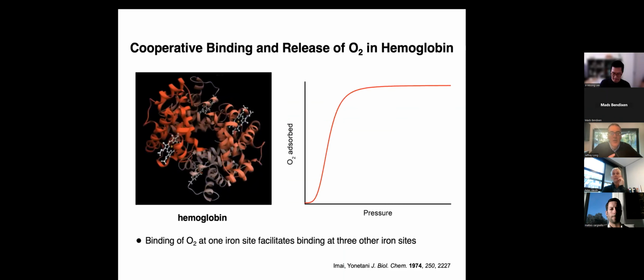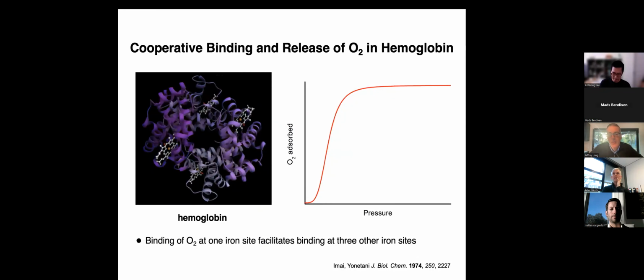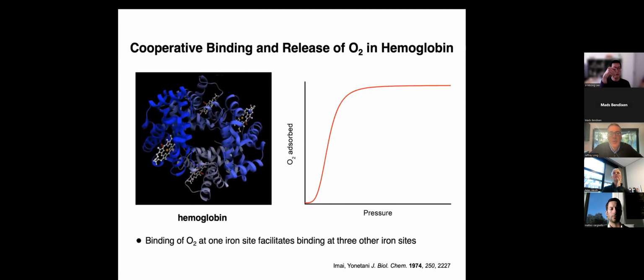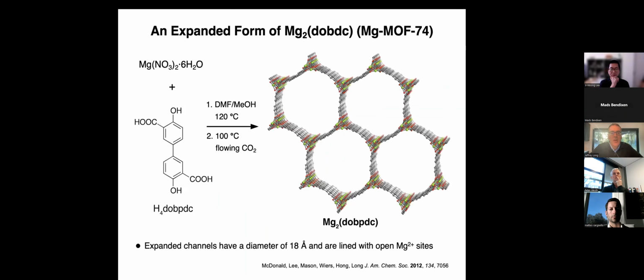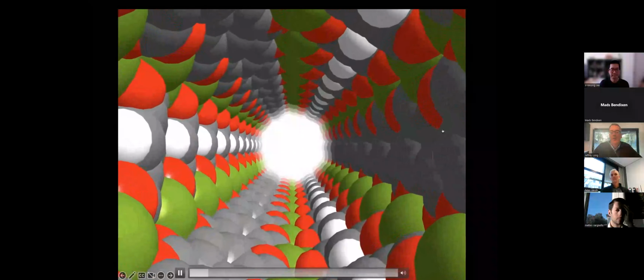And so nobody had seen this sort of thing in a dense form in a porous material until we serendipitously discovered it, not for oxygen, but for CO2. And the MOF that we found this in is one that is built on magnesium 2+ cations stitched together by this organic linker shown at the left. This linker is deprotonated 4 times, and that 4- anion stitches the magnesium ions together into a honeycomb type structure. And these channels running through the honeycomb are about 18 angstroms across.